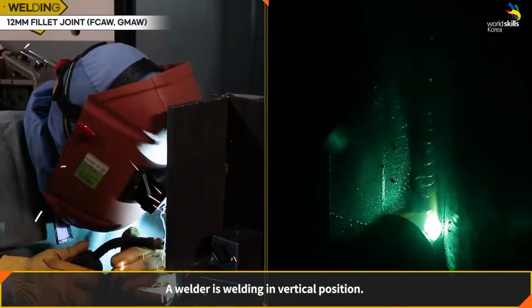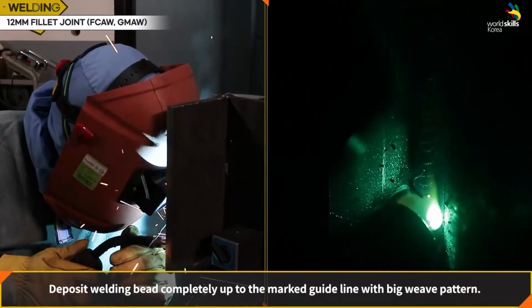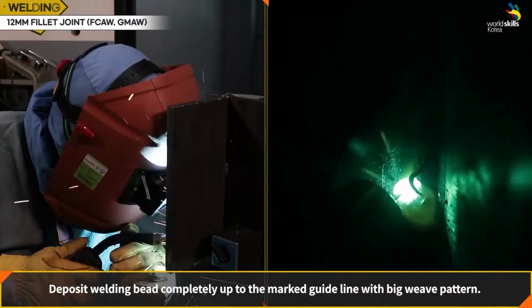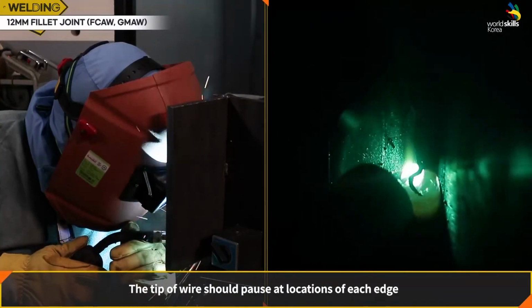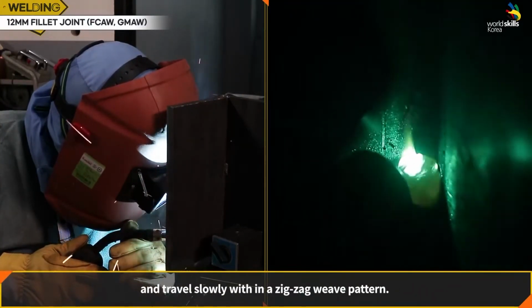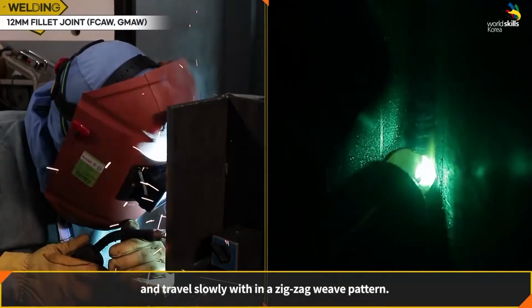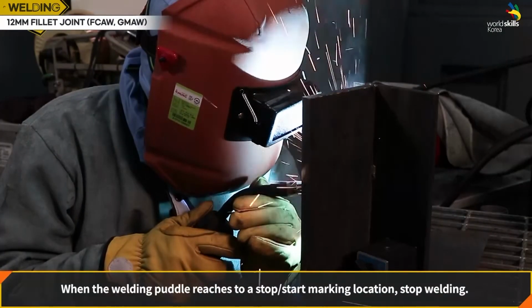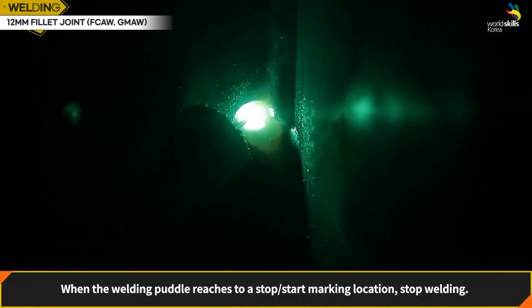GMAW vertical position cap pass. The welder is welding in the vertical position. Deposit the welding bead completely up to the marked guide line with a big weave pattern. The tip of the wire should pause at the location of each edge and travel slowly within a zigzag weave pattern. When the welding puddle reaches a stop-start marking location, stop welding.